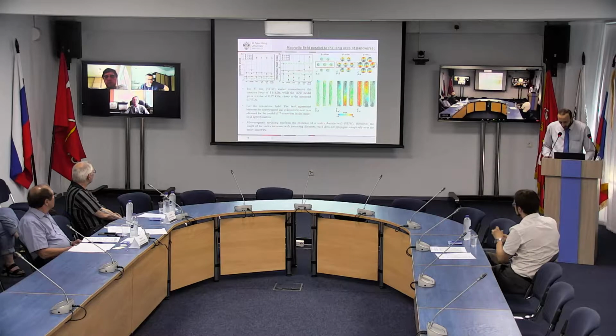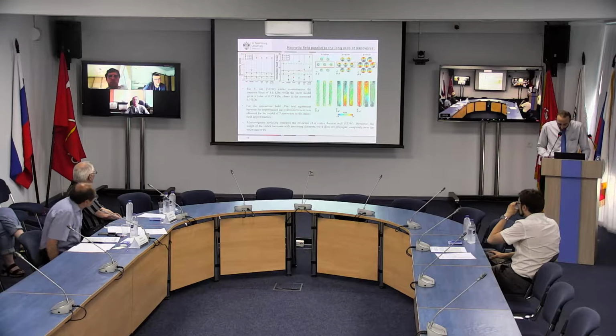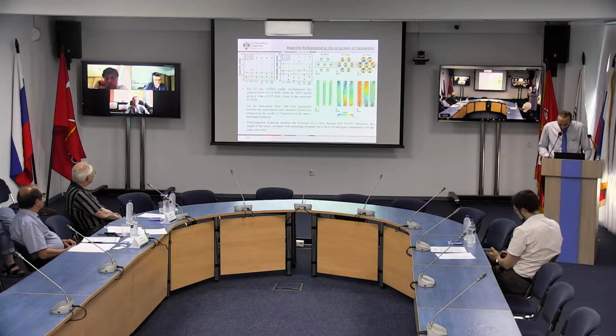Micromagnetic models, which are more sensitive to interactions and the effect of the induced field, gave almost the same coercive force, but only close to experimental values with a large diameter. In the case of 33 nanometers, the smallest diameter, the vortex domain wall model overestimates the coercive force, giving a value of 1.6 kilooersted, while the transverse domain wall gives a value of 0.97, closer to the measured one, 0.7 kilooersted.